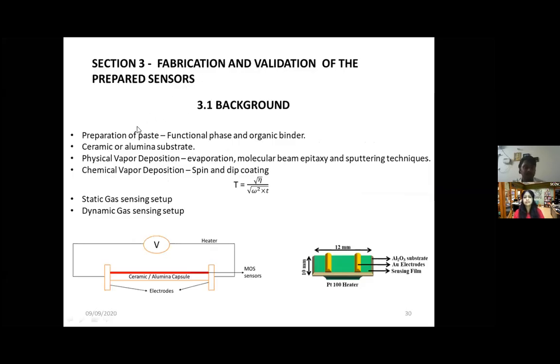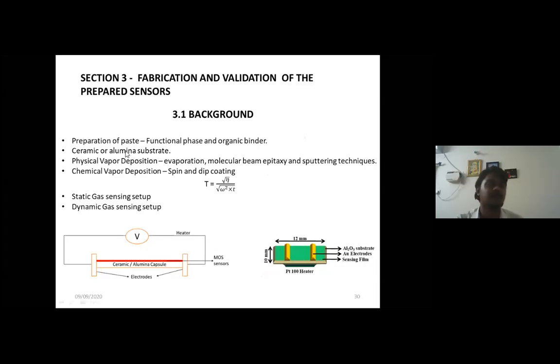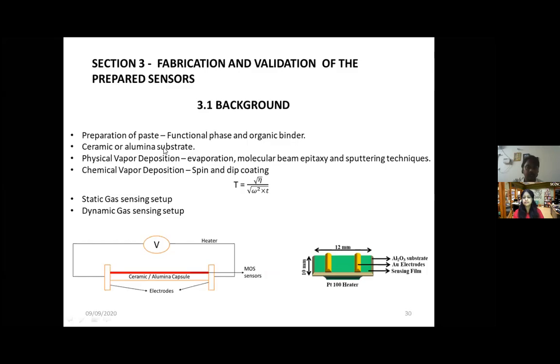So fabrication basically requires the preparation of a paste. The functional phase is the sensor material, and the organic binder is a solvent. There are ratios, such as 4:1, with which we can mix the sensor material and the organic binder to form a paste, and we need a ceramic or an alumina substrate. Since this chemiresistive sensor works at an elevated temperature, the substrate should have high mechanical strength, should be thermally conductive, and should be chemically inert. So for the temperature to be conducted to the sensor material, we use the alumina substrate, which has high thermal conductivity. So these two are required here.